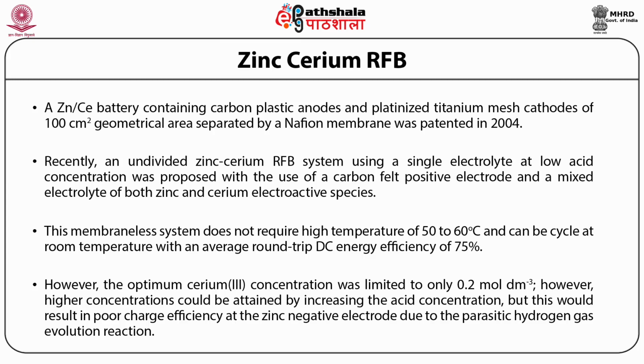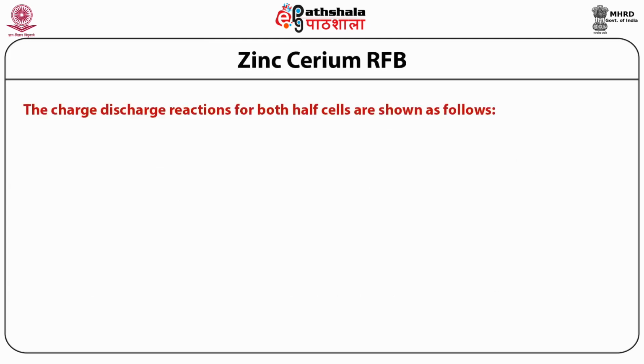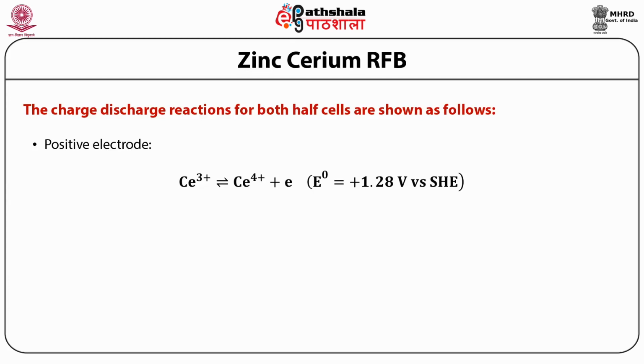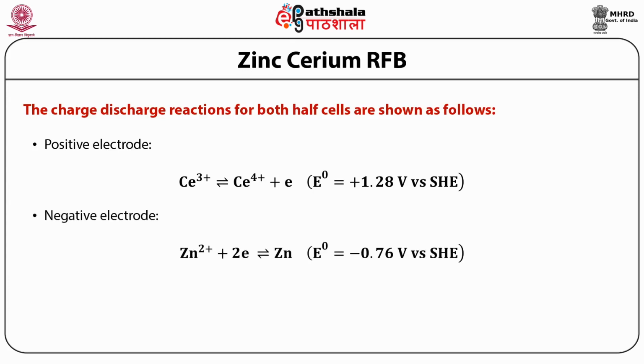However, higher concentrations could be attained by increasing the acid concentration, but this would result in poor charge efficiency at the zinc negative electrode due to the parasitic hydrogen gas evolution reaction. The charge-discharge reactions for both the half cells are shown as: at the positive electrode we have Ce³⁺ gives Ce⁴⁺ + e⁻. At the negative electrode we have Zn²⁺ + 2e⁻ gives Zn. So the overall reaction becomes Zn²⁺ + 2Ce³⁺ gives Zn + 2Ce⁴⁺.